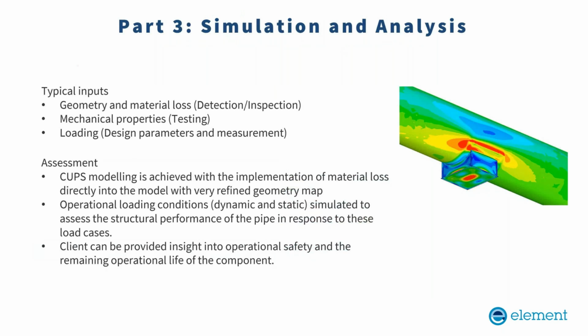The typical material data, material loss data, geometry, material property, and the on-site loading data was used as input data for the analysis. The condition of the corrosion, the material loss, the depth of the pitting, everything was used as input data for this analysis. Dynamic loading condition was simulated in the structure to perform this analysis. The data for operation condition, worst case operation condition, were also obtained from the client, which acted as input data for analysis.